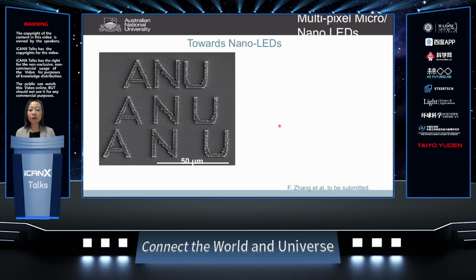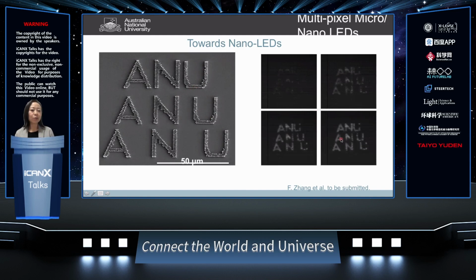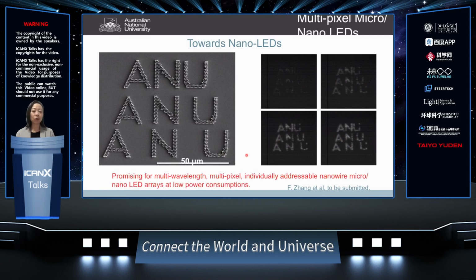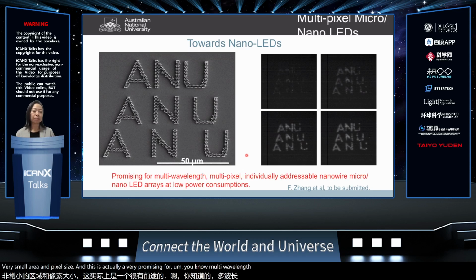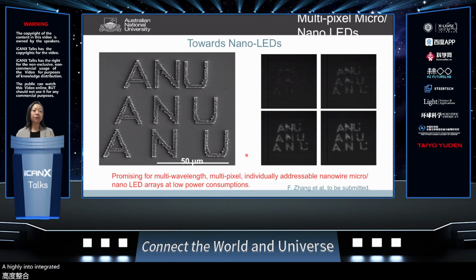So we just did a very small test, where we grew a small number of nanowires with different designs, and indeed we can see quite nice emission from just a few tens of nanowires, showing that they can be made into a very small area and pixel size. This is very promising for multi-wavelength, multi-pixel individually addressable nanowire LED arrays, which probably have lower power consumption and are more highly integratable for applications.